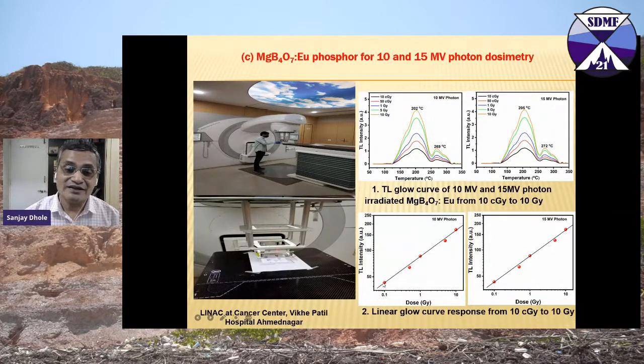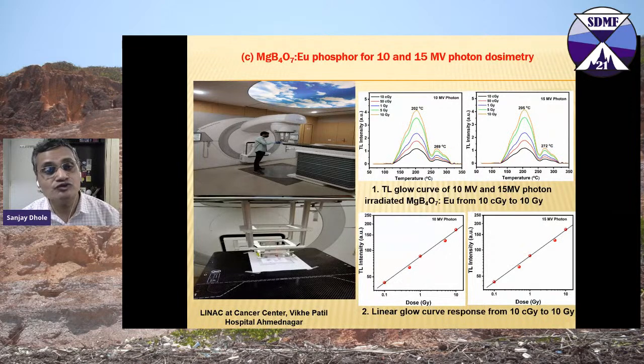See that the material that we could develop can give you the 10 centigray to 10 gray, and this kind of nanophosphor can effectively be used for the cancer treatment, where the maximum dose which can be delivered to the tumor for one set is only 1 gray or 2 gray, and the total dose which is to be received may be more than 30 gray or so.